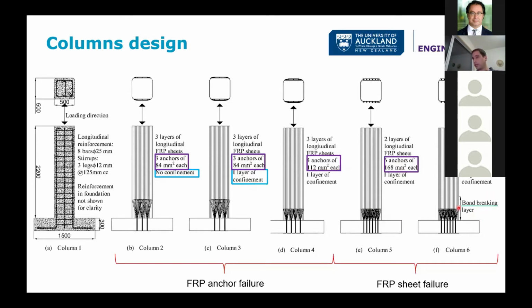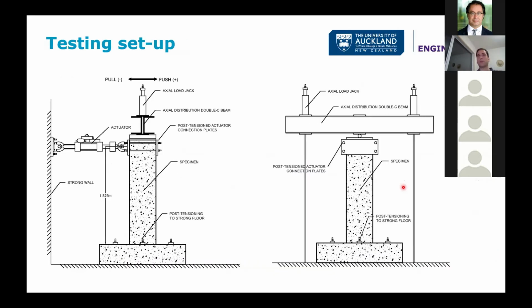Finally, in column 6, I used a bond breaking layer at the bottom half meter, because we observed in these 4 columns high asymmetry, and the FRP would debond in the compression cycle by something similar to buckling, instead of the tension cycle by slowly debonding.